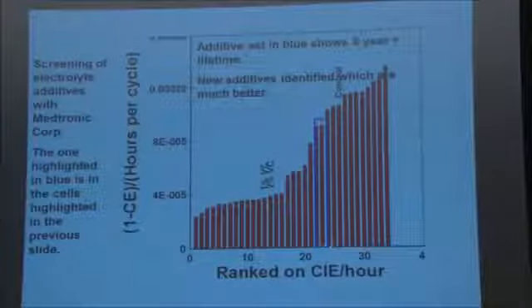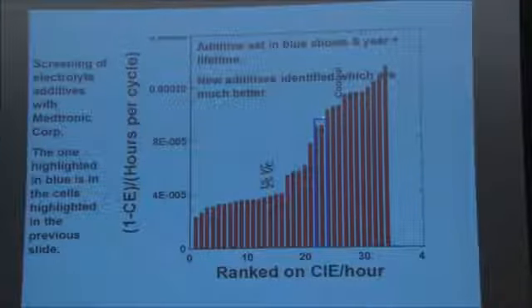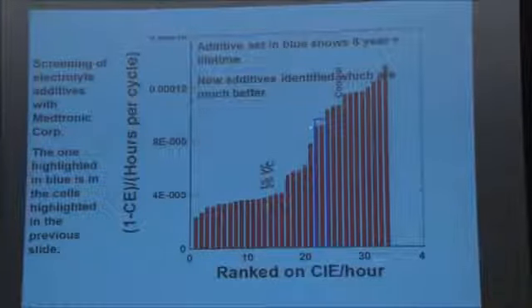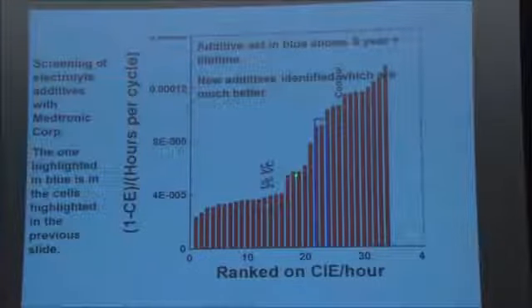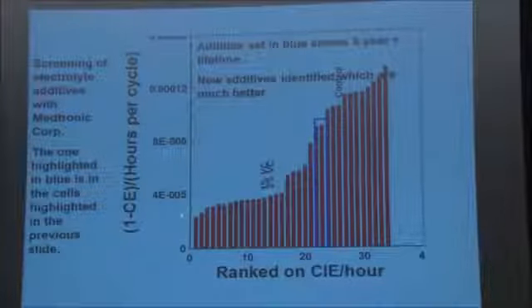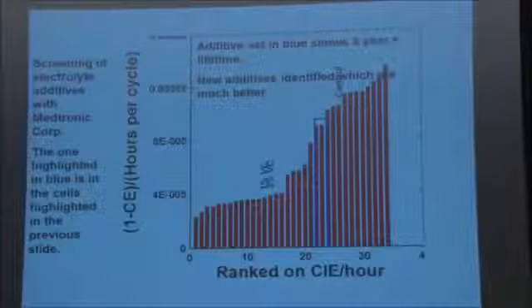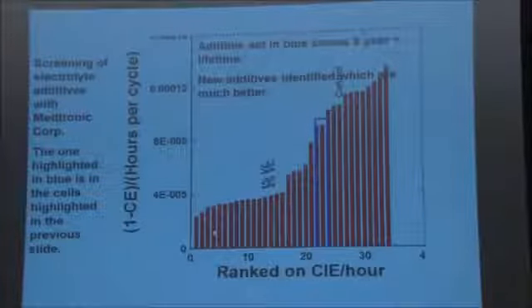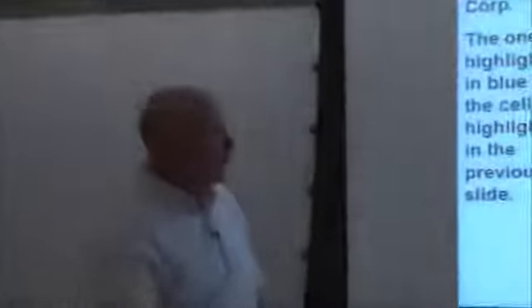And the data that I showed you on the previous slide is for the additives set in the blue box. So we've identified additives that are much, much better than the one in the blue box. And Medtronic's taken the ones at the bottom and set some cells off for long-term cycling. And they'll, of course, be better than the one that already demonstrated 5 years of testing. So the point is, in a few weeks, you can identify things that are way better than what is currently being used.